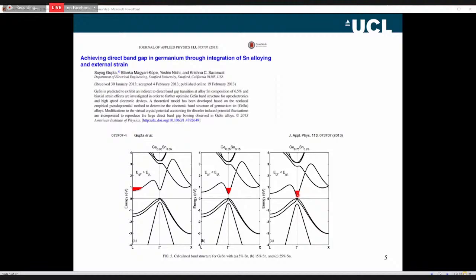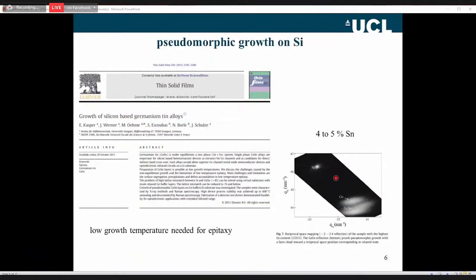In practice, it's a little more difficult. The reason why it's more difficult is that tin is such a large atom. It really doesn't like to sit in a germanium lattice. So when you grow this material, tin tends to surface segregate. If you try to incorporate tin into the lattice, the tin just sits on the surface, and it causes problems for growth. So I've picked another paper here, still in the background of this material system.